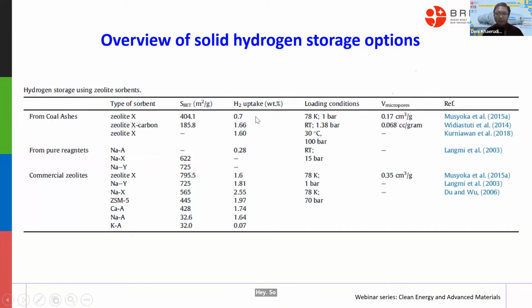So this is the condition of the hydrogen uptake. Again, compared with the previous, like the carbon fiber, it is still lower. But we have the valuable fly ash from the power plant industry and many other activities. If we utilize it for this application, I think it's very good. So this is the loading condition, like 78 Kelvin, the liquid nitrogen condition at 1 bar. But this one is at room temperature and 1.38 bar. The hydrogen uptake or storage capacity is about 1.6. And this is the micropore.